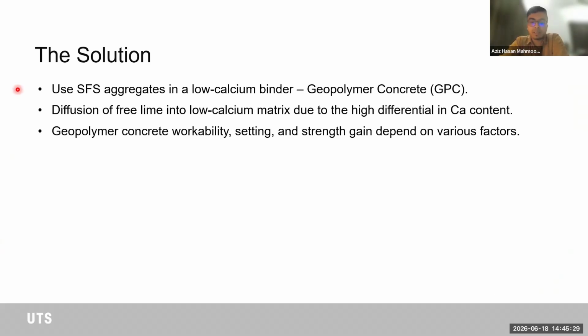Now, with your typical cement that you get out of cement manufacturers, the calcium oxide content is quite high. It ranges from 60 to 65% if you run a chemical composition of the cement. But we can use geopolymer concrete, which doesn't involve any cement at all as the binder. So we picked fly ash and ground granulated blast furnace slag, which are industrial byproducts as well. Fly ash comes from coal-powered power plants, and slag comes from steel industries as byproducts.